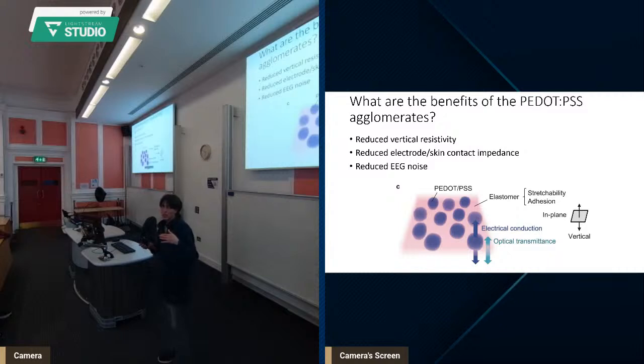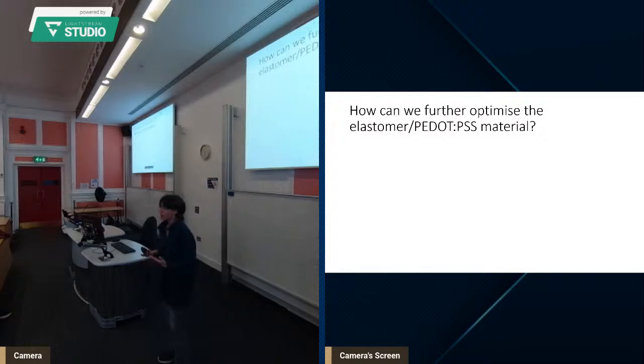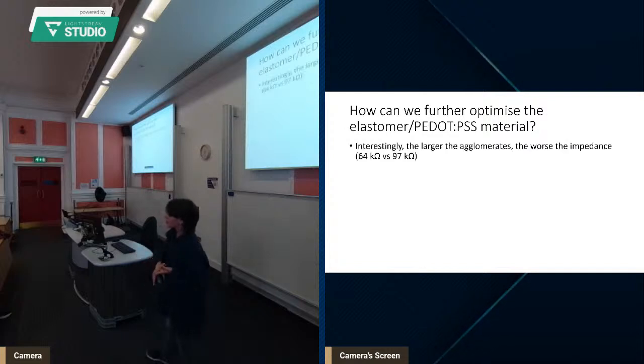So rather than the electrical signal moving sideways within the plane of the sheet, it goes vertically, so it goes straight through the sheet and then out to the electrode that'll pick up the signal. So how can we further optimize the elastomer PEDOT PSS material? Once again, we want to improve the elasticity, we want to improve the conductivity, and we want to improve the adhesion. So the larger the agglomerates, the worse the impedance. So what this means is that when the PEDOT PSS splotches, I guess, are larger, the signal is worse.